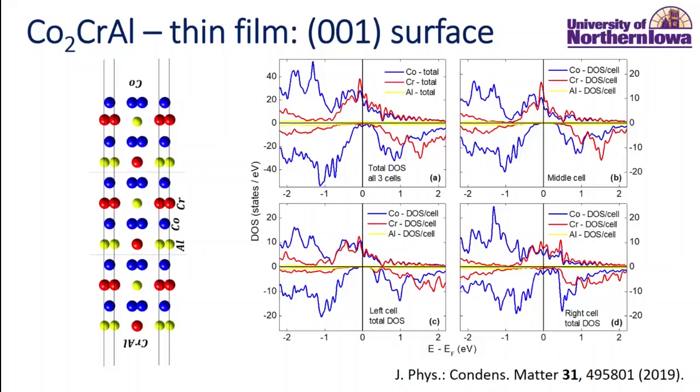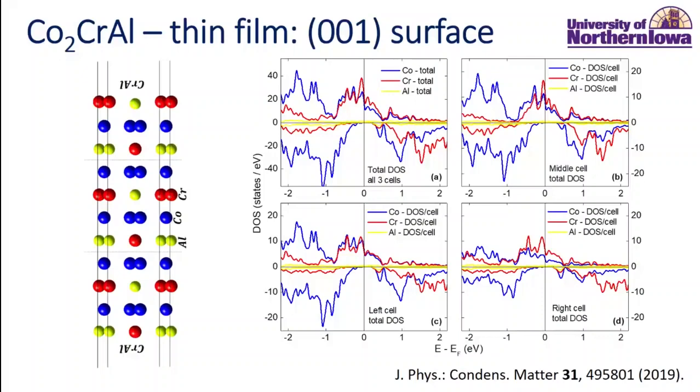So we can clearly see the difference, and this is again one of the main results of this work, right? So here, this is again total density of states, and here we see additional states that appear in the minority spin channel. And then next slide, same calculation, total density of states, entire cell. We just remove one layer, and those states disappear, right? So this shows that the detrimental effect on half-metallic properties of this material is essentially entirely due to the presence of that cobalt layer.